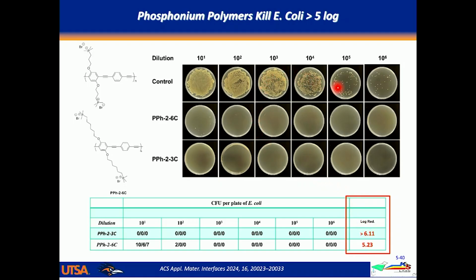And what I'm showing here is a classic biological experiment where we're actually plating out the bacteria, and you can see this polymer, these are 6 log dilutions. You can see no growth of bacteria. So it's basically just wiping out the bacteria completely at 20 microgram per milliliter, and this is about a 20-minute light exposure in this experiment.